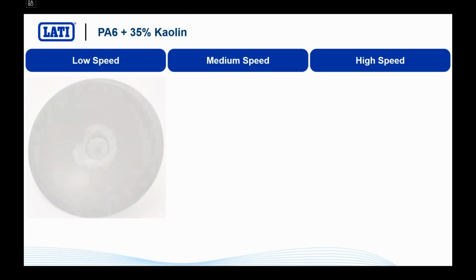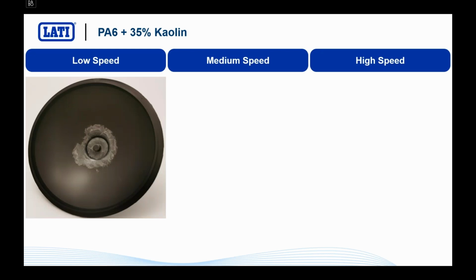The last filler, kaolin. Kaolin, as I told you before, is a nice filler, but it is quite difficult to properly disperse into the matrix. So it somehow pops out of the matrix. It can create a lot of issues. So you see the surface here with low speed is dull. You have a very bad looking spot around the fan gate.